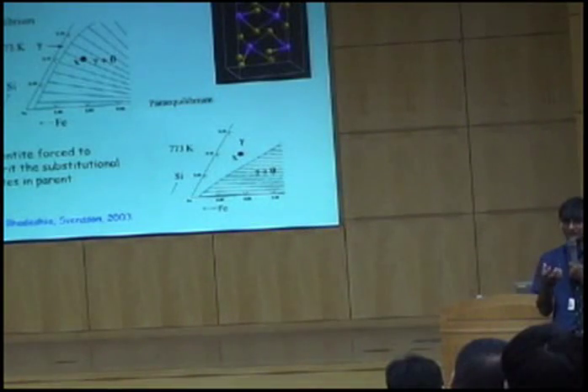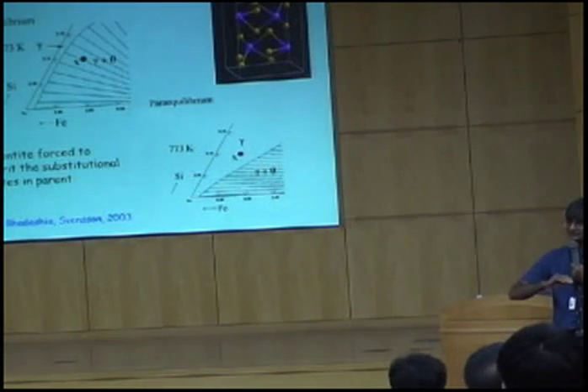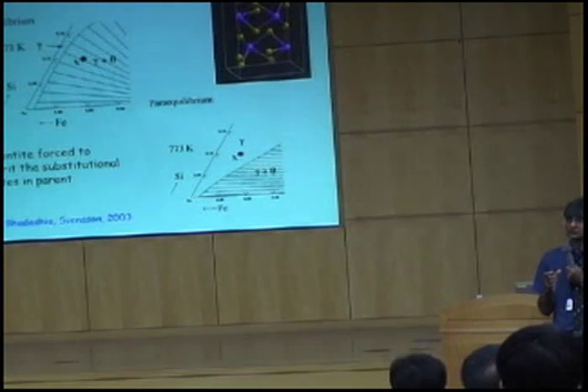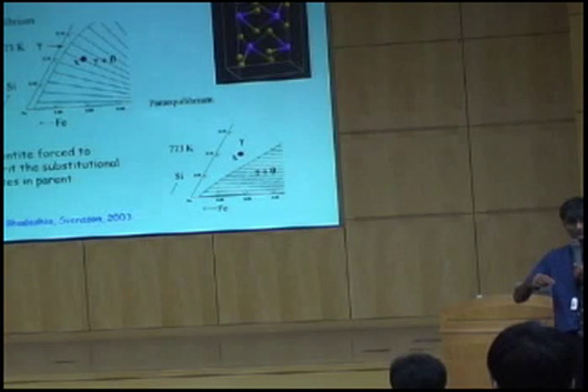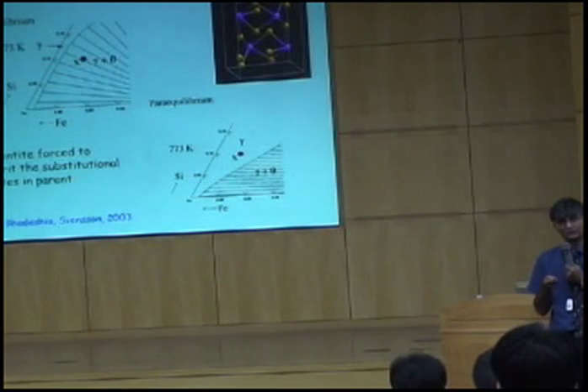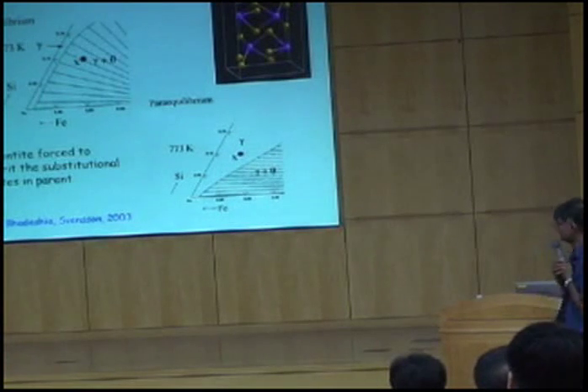Okay? Silicon and aluminum prefer not to be inside cementite. But remember that bainite and martensite form at a low temperature. So diffusion of silicon and aluminum is not possible at those temperatures. So when cementite precipitates, it's forced to accept the silicon. Okay? So it is forced into the cementite structure.